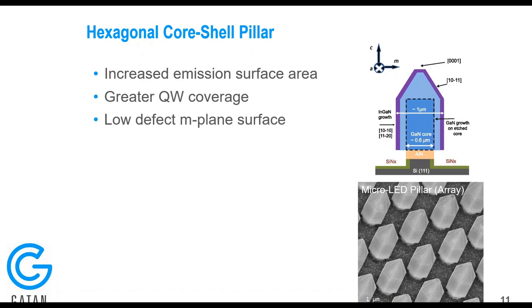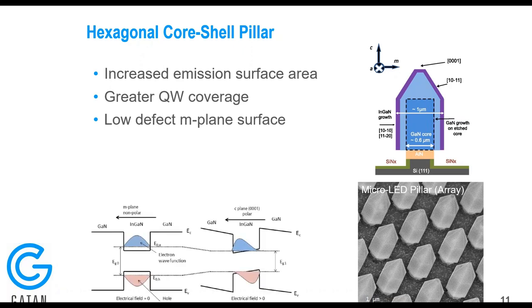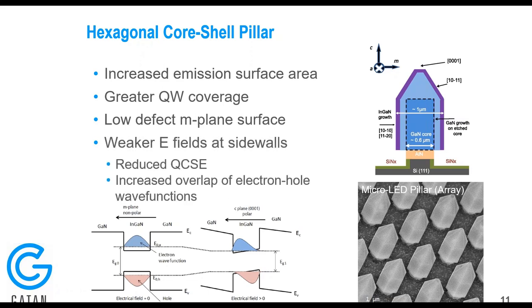It also allows us to access the low defect M-plane surface, which is along the vertical on the pillar. What you can see here is the band diagram along the M-plane versus the C-plane. So the C-plane is the top of the pillar and the M-plane is perpendicular to that. What we see is that there's a polarization that takes place and leads to an electric field, which causes the overlap in the electron hole wave function in space to be less aligned in the case of the polar plane, or the C-plane, on the top. So by reducing the electric field at the sidewalls, we've increased the overlap of the electron hole wave function and led to a more efficient recombination of electrons and holes on that surface.